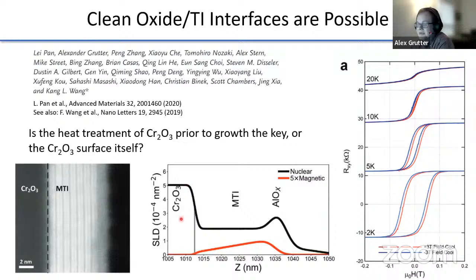It may actually be something to do with the chromia surface itself. We don't know. But what we did definitely find is that you have a very sharp, high quality interface, no transitional growth region, and strong interface coupling. So it was possible to get exchange bias across the antiferromagnetic interface with a chromium doped topological insulator.